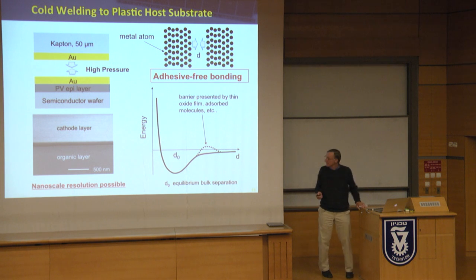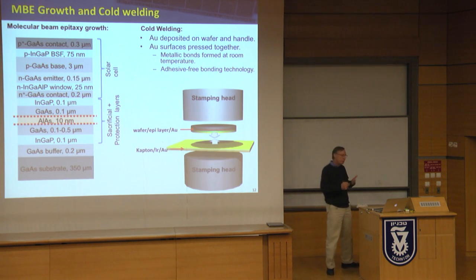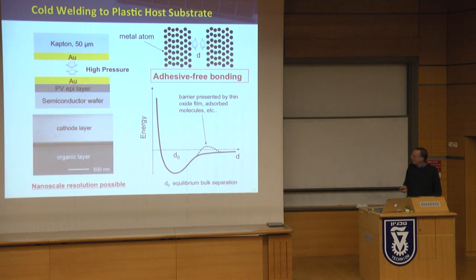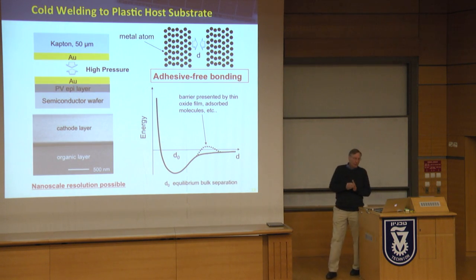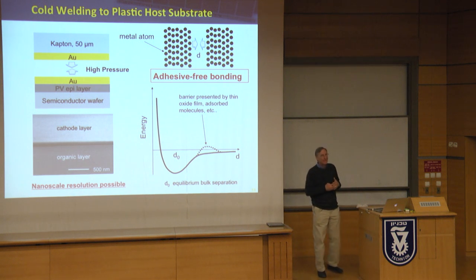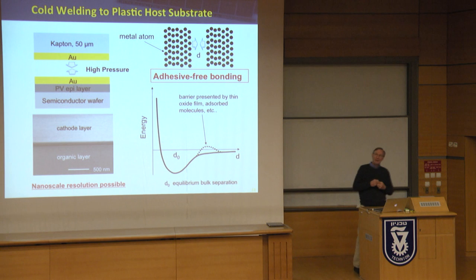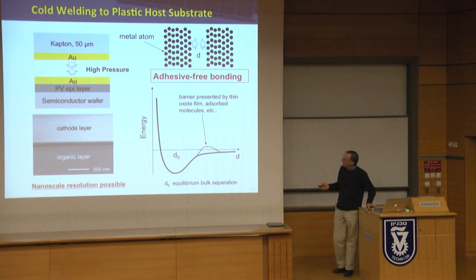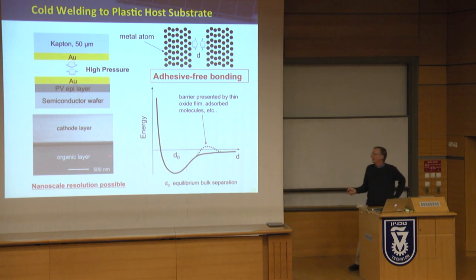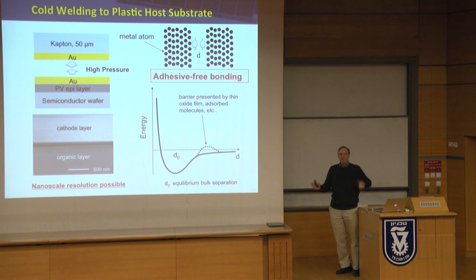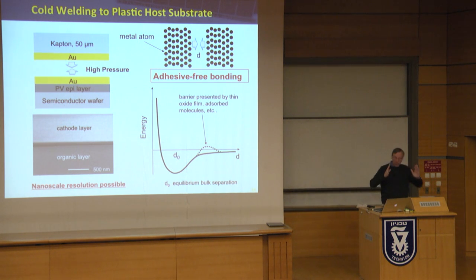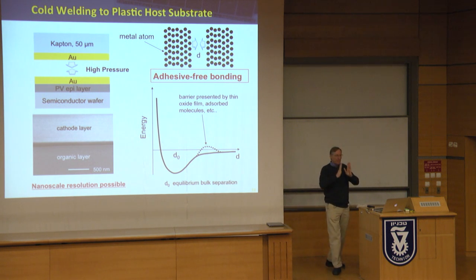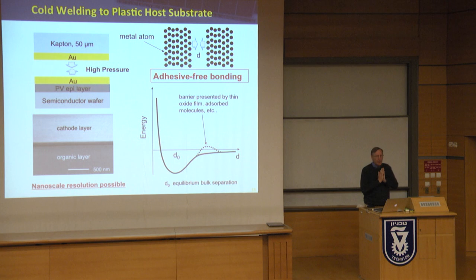Now the cold weld process that's shown here, basically you take 2 clean metal surfaces and you press them together. This was something that I learned how to do in Bell Labs when we were putting LEDs on headers. But we simplified it greatly. We then moved that process to making OLEDs by putting down the contact here. Basically, when you take a noble metal and you press it together and you shrink that distance d, there's basically a bonding energy, but there's some surface contamination. You have to press through it. It takes a little bit of pressure. If it's clean, it doesn't take a lot.